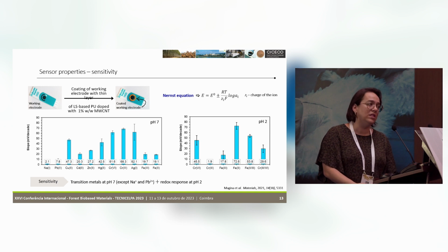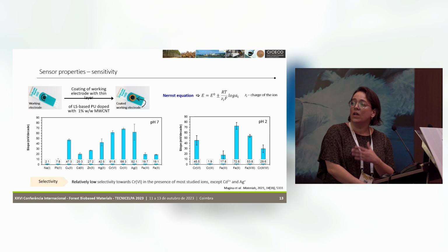Although there is high sensitivity, these sensors display some relatively low selectivity that should be improved towards chromium-6, except for cadmium and silver. So based on these very promising results, the possibility of producing sensors from lignosulfonates with other carbon nanofillers was tested, including...